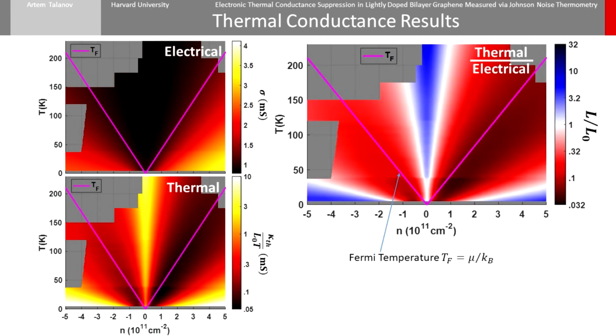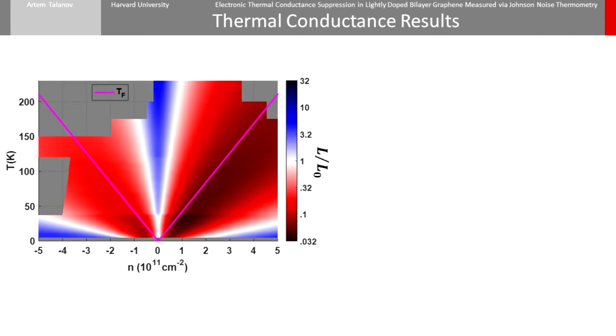We compute the Lorentz ratio by dividing the thermal conductivity by the electrical conductivity, and we get the following plot, which I am also showing on a log scale. Note that white indicates the Lorentz ratio is equal to 1, blue is larger than 1, and red is less than 1. I've indicated for each density the Fermi temperature. Above this temperature we have coexisting electrons and holes, and below we have a degenerate semiconductor. We will now examine this data more closely.